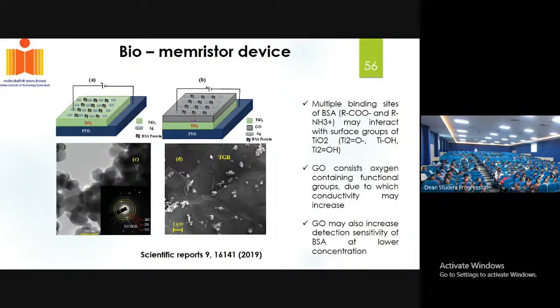Basically, what we have done is we try to attach these biomolecules, the bovine serum albumin, on top of the titanium dioxide based devices. Here we develop two kinds of devices: the titanium dioxide based devices, and then on top of that, we also try to attach graphene oxide to enhance the stability and to enhance the resolution or the sensitivity of the device. So this is the kind of device that we have developed. This is the SEM picture of the device that we have developed. As you could see here, the white patches. These white patches are basically the bovine serum albumin which we attach to the device.